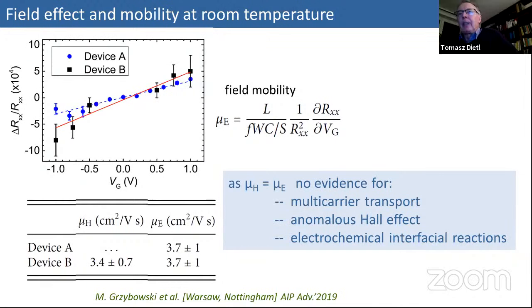Yeah, but exactly, good points. This is the case of the crystal Hall effect you introduced, this notion that you may have very small magnetization due to small canting, but actually huge anomalous Hall effect. Not in this case. In the case of gallium manganese arsenide, it would not be the case, from what you say, from the canting. Otherwise, it would be zero. It would not be allowed by symmetry. Once you put the magnetic field, of course, you break that symmetry.